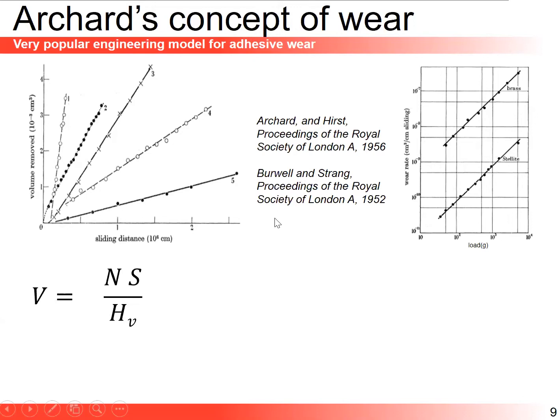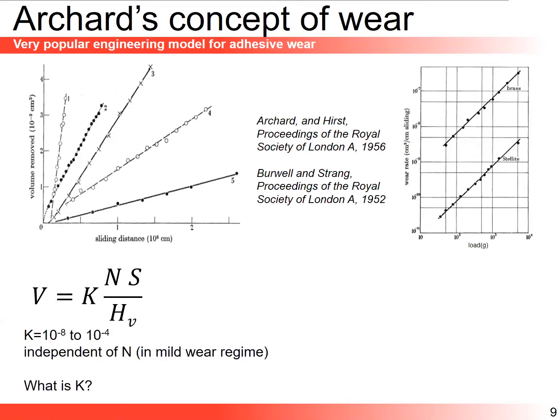The only problem is that, and we go back to where this theory emerges from, a micromechanics description of why this equation comes to us. But the only problem is, to match this theory to experimental data, you need the famous K fudge factor. And this K fudge factor is not a small correction. It's not a 20% correction. It's not a factor 2 correction. Hell no, it's not even a factor 10 correction. It's a correction, let's say, of 6 orders of magnitude. So it's a gigantic correction. And we don't know what K is. So to me, it's a major problem.